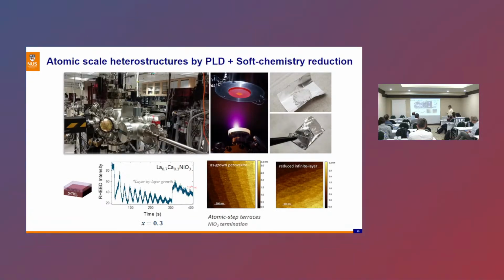So what we do in our lab is pulsed laser deposition. People have also done it using molecular beam epitaxy. And this is how our system looks. This is subsequently followed by apical oxygen removal by calcium hydride soft chemistry reduction. As you can see here, the perovskite structure is perfectly fine, as you have this RHEED oscillation showing that you have really layer by layer growth of the perovskite structure. Looking at the surface of the substrate before and after the growth, and even after reduction, you can see this nice step of the STO substrate, which indicates that, at least in terms of the perovskite structure, you should not have a problem reproducing the sample.